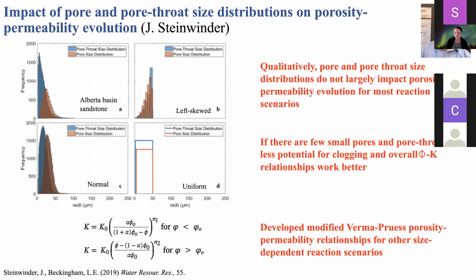We've done some other related work to this, looking at what about variations in pore and throat size distributions. So this was done by my master's student, Jeffrey Steinwinder. We looked at an Alberta Basin sandstone shown here, and then several synthetic pore and throat size distributions, just seeing if the shape of these distributions changed, how would that impact the evolution of porosity and permeability?